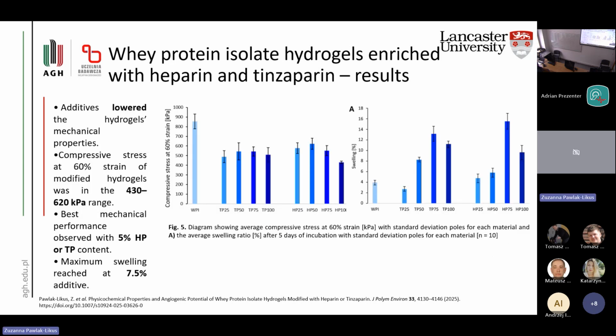Here we have mechanical properties and swelling. On the left, there is a graph showing average compressive stress at 60% strain. And on the right, there is the average swelling ratio after 5 days of incubation. It was predicted that additives would lower the hydrogel's mechanical properties as they increased the porosity. This is also visible in swelling, as increased porosity influenced the swelling of hydrogels, and the maximum swelling was reached at 7.5% additives for both tinzaparin and heparin.